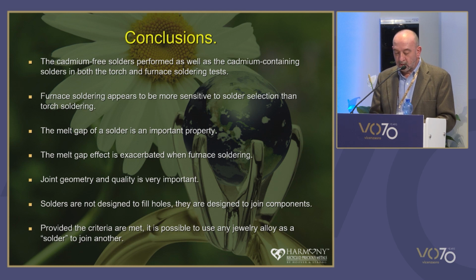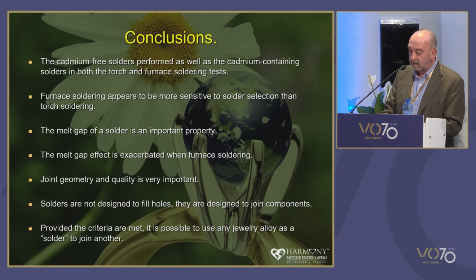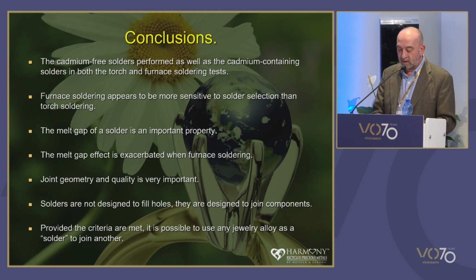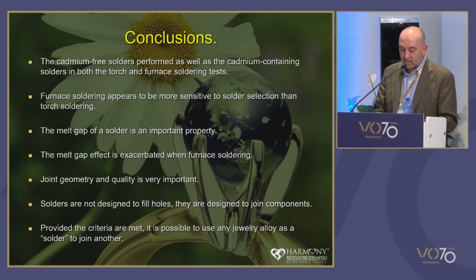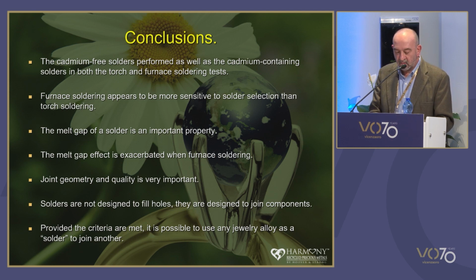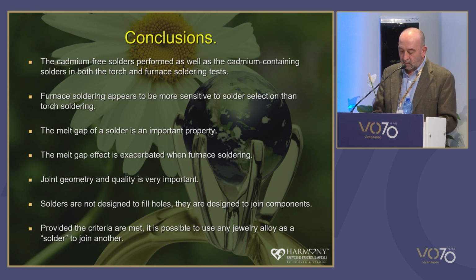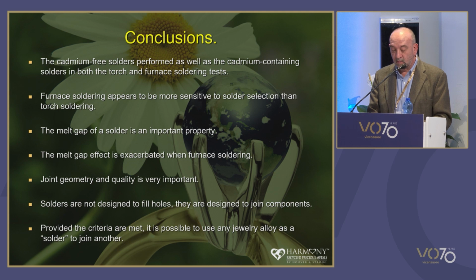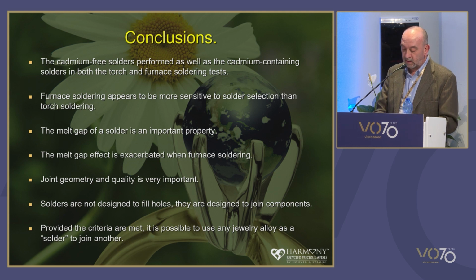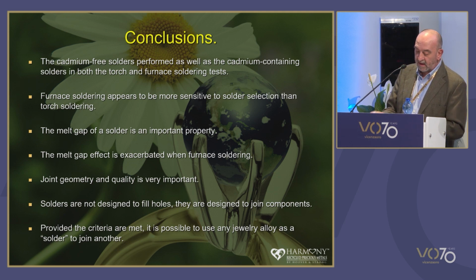So cadmium-free solders perform as well as cadmium-containing solders in both torch and furnace soldered tests. Cadmium is known to help with wetting and flow, but the results showed there was no real difference. Furnace soldering appears to be more solder sensitive when you select your solder, and more so than torch soldering. When torch soldering, jewelers have total control of the heating and the soldering operation.